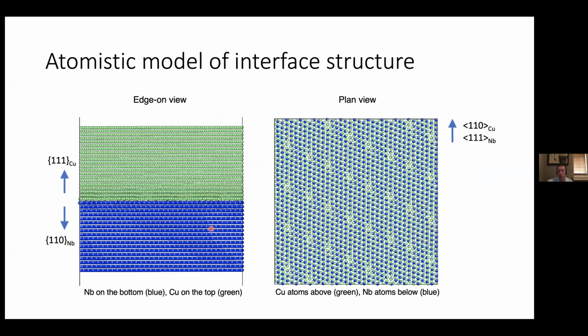So if we were to look at the PVD interface, here's the PVD interface, again looking edge on over here. On the right, I'm showing you a top-down view looking into the interface plane of this copper niobium interface. You can already see just by eyeballing it that it has this sort of quasi-periodic structure in it. But if you do a more detailed analysis, you can figure out that this quasi-periodic structure is the outcome of misfit dislocations that are present in this interface structure.